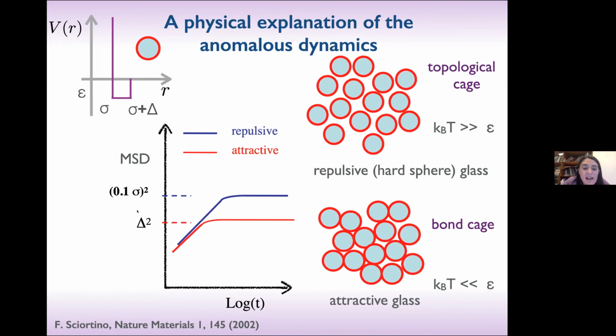So if your delta, if your range of the attraction is very small, it will be sensibly smaller than the one in the repulsive glass. And so you actually have the competition of the two states. This is the important ingredient, and it is why it happens only in short range attractive colloids, that you have to have a clear separation between these two landscapes.